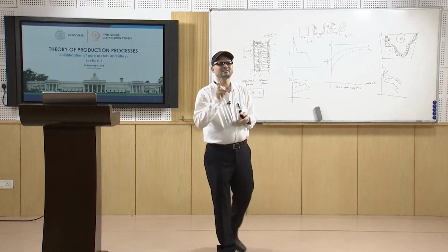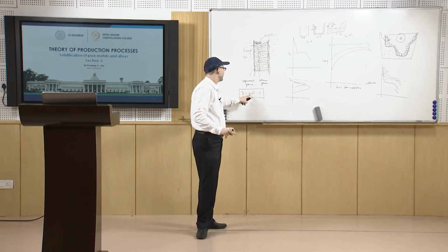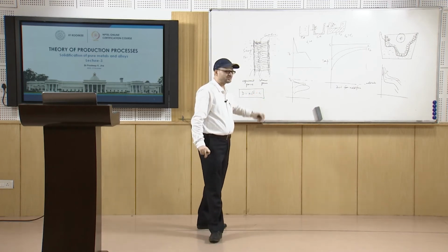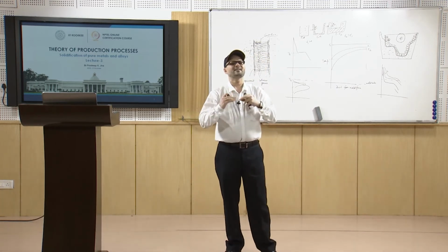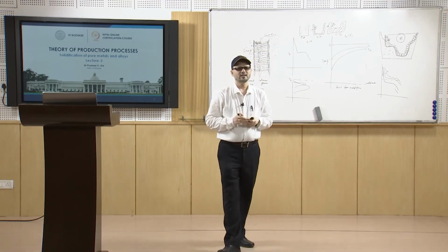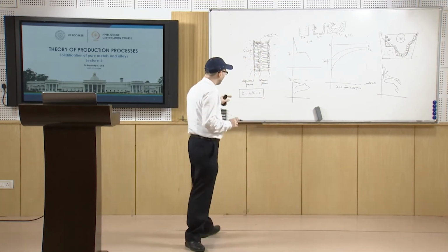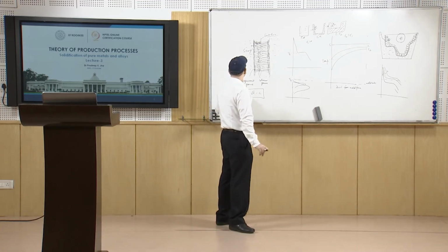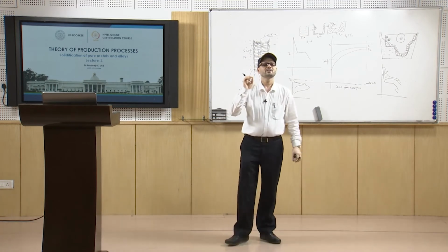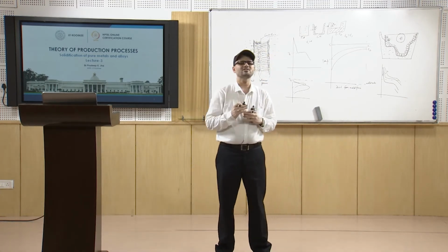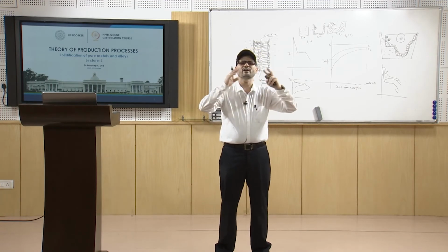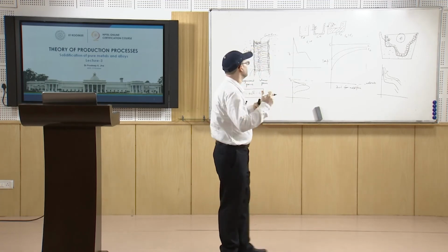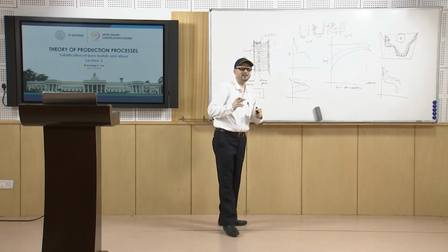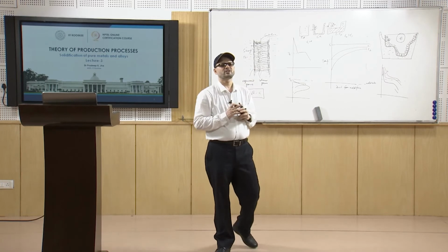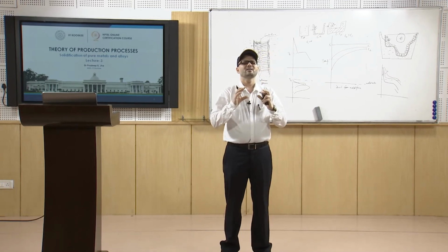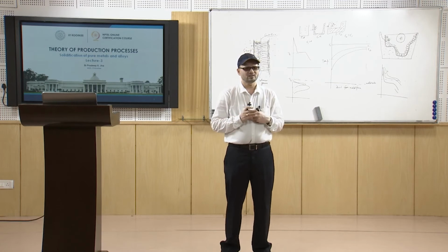So, based on that, the constant K will depend upon, and this C is largely determined by, the degree of superheat. This way you can find the value of the thickness of the solidified shell. Further, if you analyze the solidification time for a casting, it is seen that the solidification time is proportional to the square of the ratio of volume to surface area of the casting.